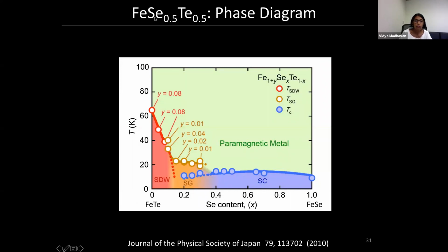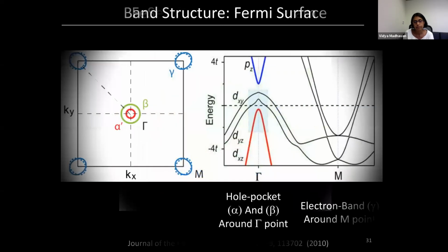It's an alloy of selenium and tellurium. So one end of this phase diagram, which is the FeSe end, is actually a superconductor. The other end of the phase diagram, which is the FeTe end, is a spin density wave system, or think of it as an antiferromagnet. Now, when you create this alloy, as it turns out, somewhere in the middle right here is where the interesting Majorana physics happens. This is where the material becomes topologically non-trivial.